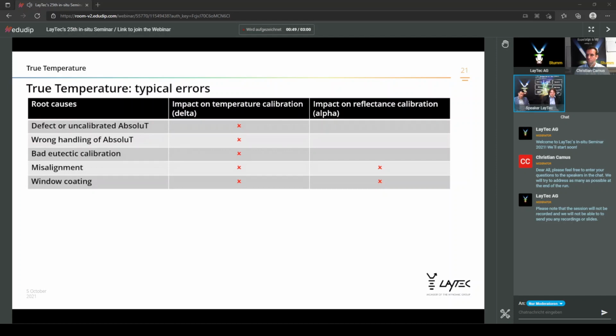This function comes in very handy as a helpful tool to support regular maintenance and keep a close eye on the gradual effect of window coating. Even damaged or broken parts within the entire viewport assembly can easily be detected by a significant sudden jump in the resulting alpha value. It's easy to imagine that if there's a severe coating on the window or anything else is impacting the transmissivity of the viewport, a subsequent alpha calibration will result in a very high alpha value. So it leaves the typical gradual development of the alpha curve and shows a sudden jump.